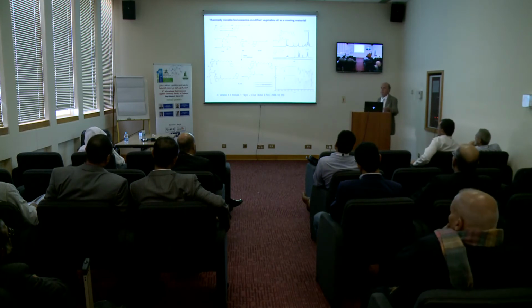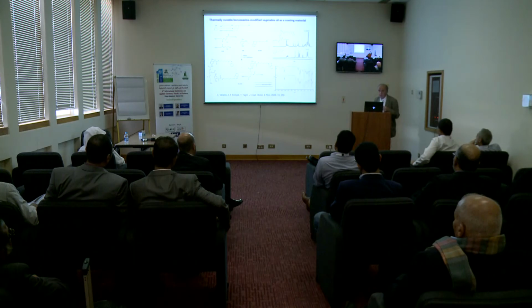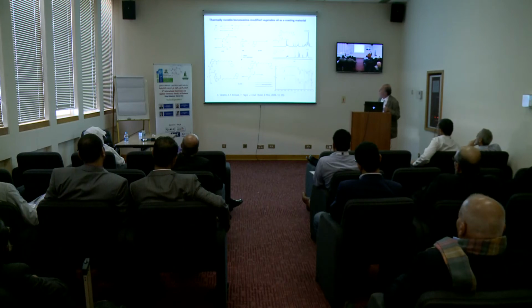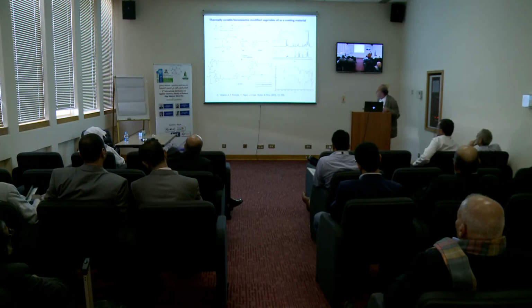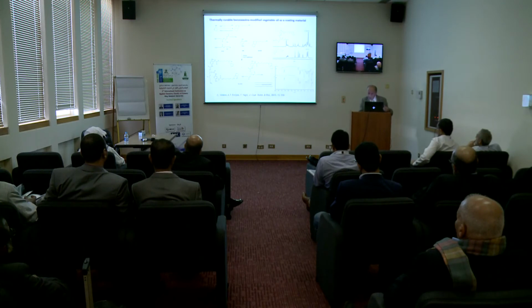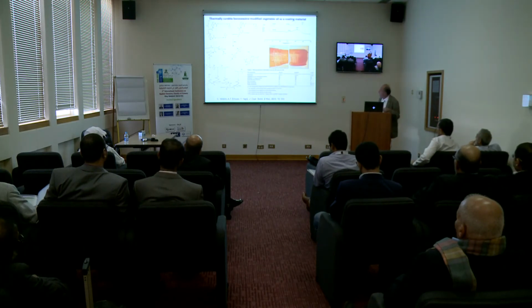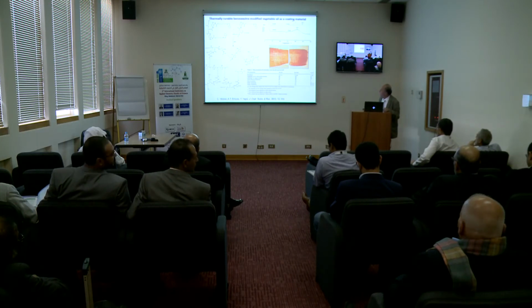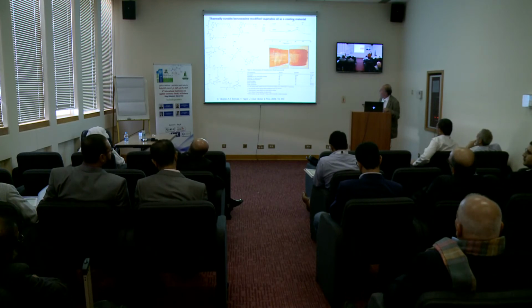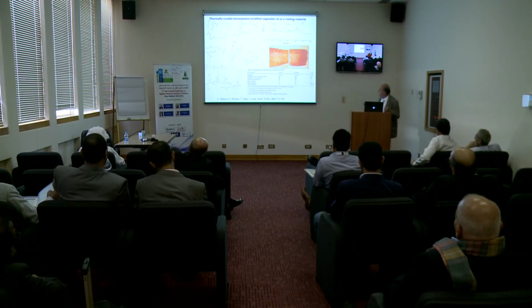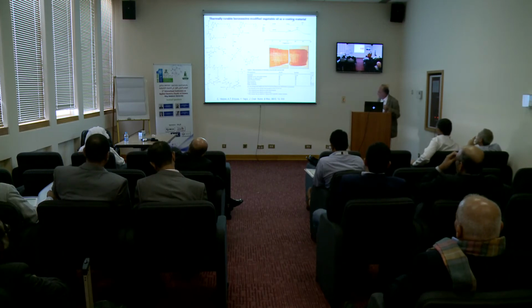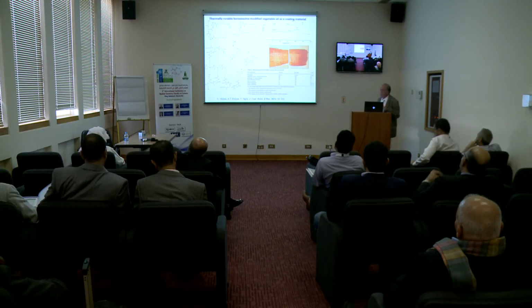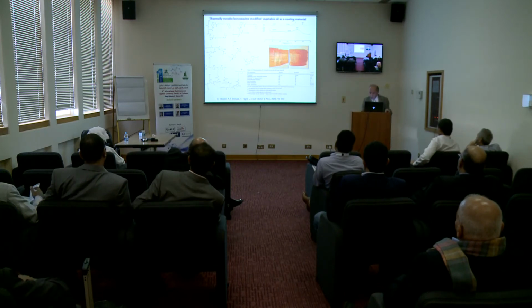Another concern in environmental systems is to use renewable materials like vegetable oils and so on. We were able to prepare polybenzoxazines from modified vegetable oils as coating materials. Maybe the chemistry is too complicated here, but we were able to have such systems nicely. Sometimes you need to have a strong adhesion on the wood surface for coating applications. So we made a scratch here, and you can see they do not peel off, and they are really good materials for wood coating with high thermal stability.